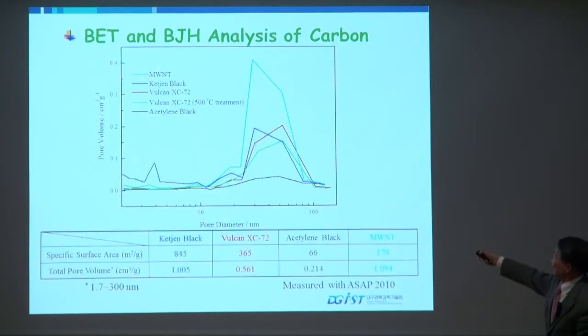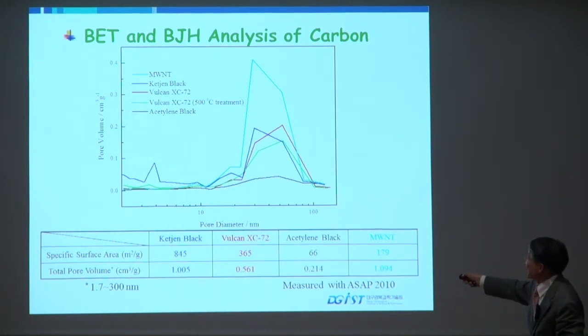And we tested the different carbons: multiwalled carbon nanotubes, Ketjen black, Vulcan, Vulcan temperature treated, acetylene black. The crystallinity is good like this. Of course, the carbon nanotube is even higher. Then we measured surface area, pore volumes, and pore diameter distribution. And this is 100 nanometers, and this is 10 nanometers. So this is very, very micropores on this side, and this is mesopores. And when you see this, Ketjen black has a very good fraction of micropores. But carbon nanotubes, the multiwalled carbon nanotubes, have almost no micropores, but a very big fraction of mesopores. Okay?